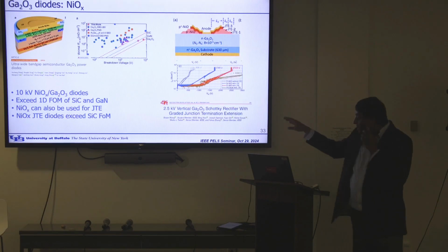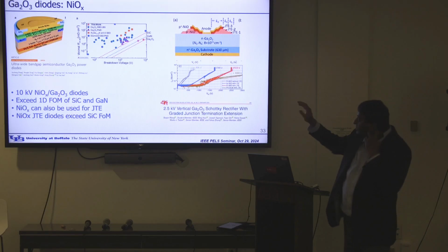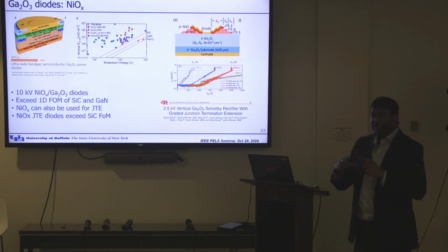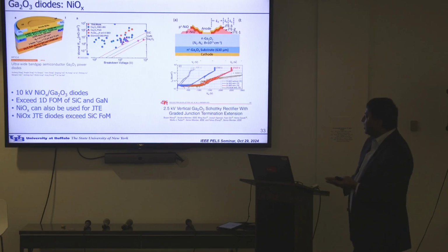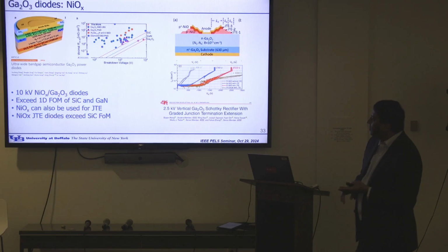So some of other work from other groups. This is using nickel oxide. This is what I mentioned. Nickel oxide is actually a P-type oxide. It's a 3.2 or 3.4 eV. Holes are not very fast, but there are holes, right, which conduct. And you can see on the left here, it's a 10 kilovolt nickel-oxide, gallium oxide device published.